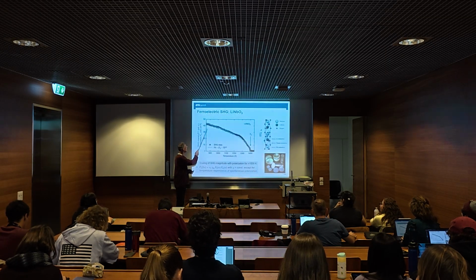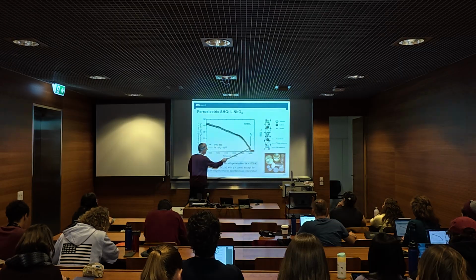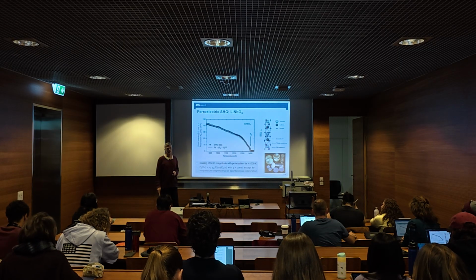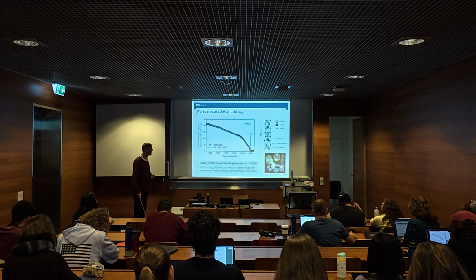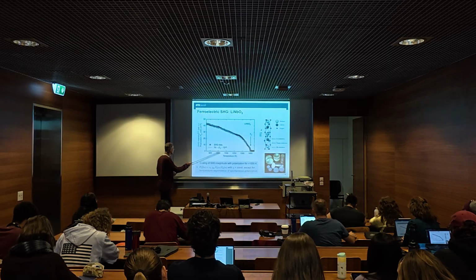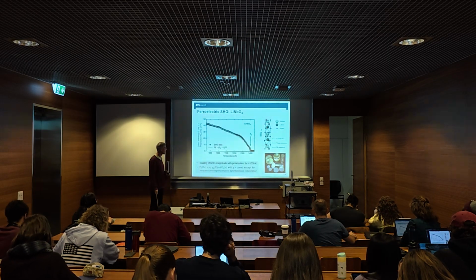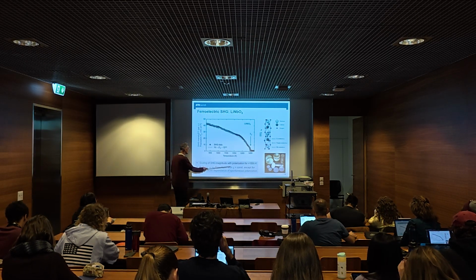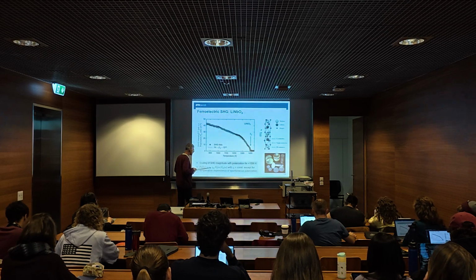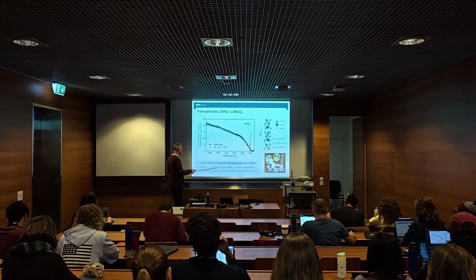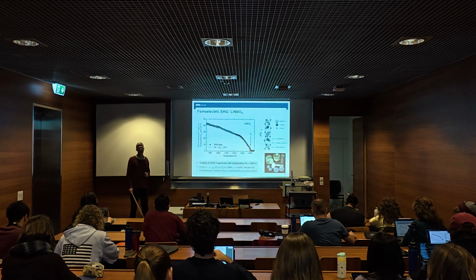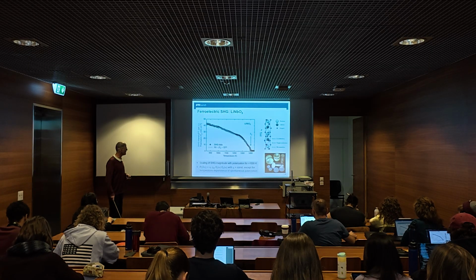So this is really a very pure picture of the polarization in your sample, the intensity of the second harmonic line, of this frequency doubled line, as you can see in this plot, across more than 1,000 Kelvin. Here it says chi, so this susceptibility is constant except for the temperature dependence of the spontaneous polarization. So very nice technique therefore.